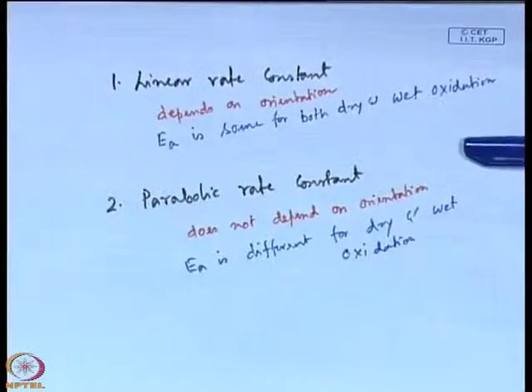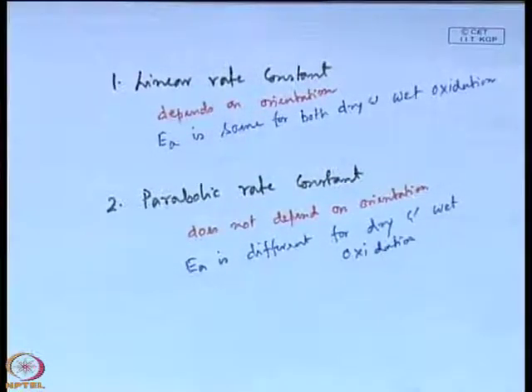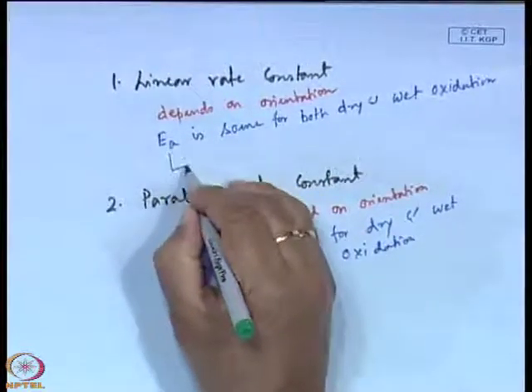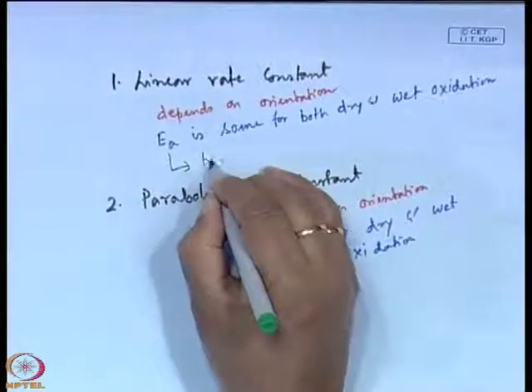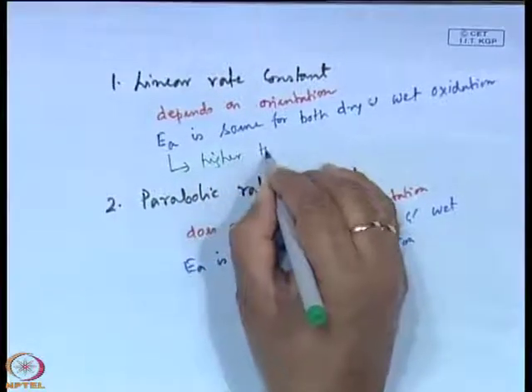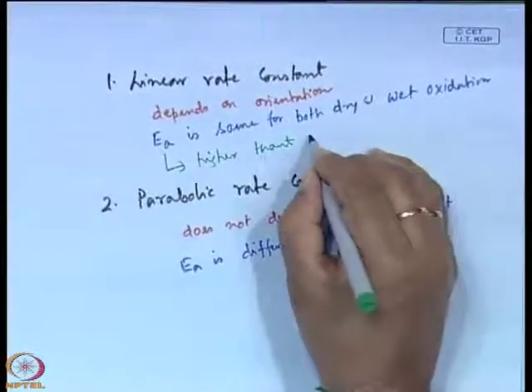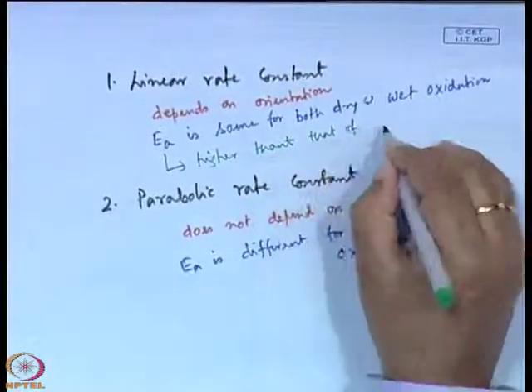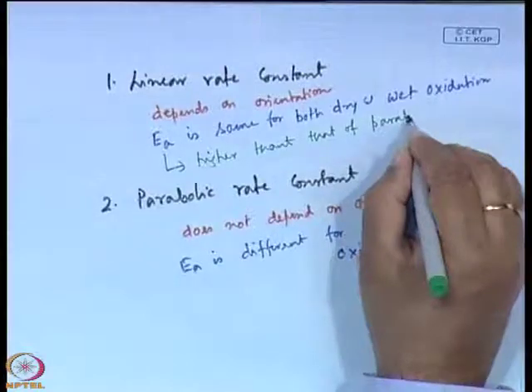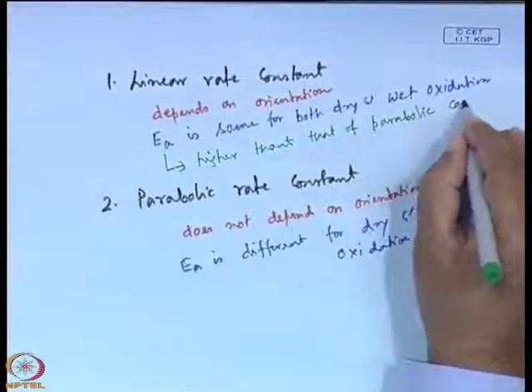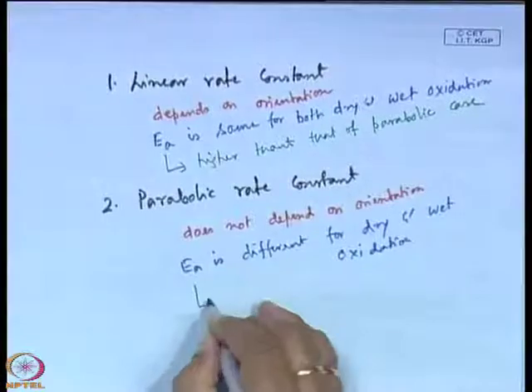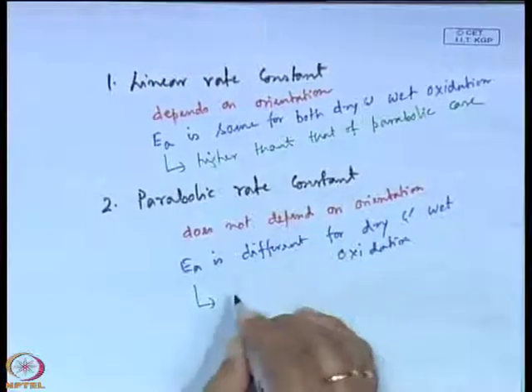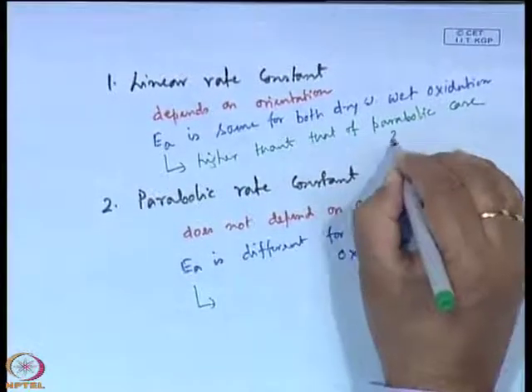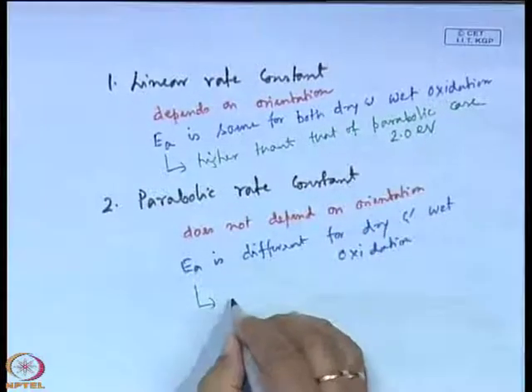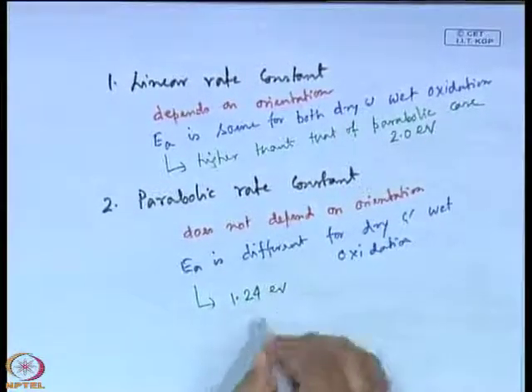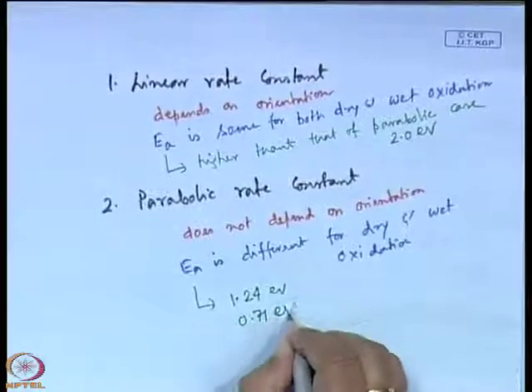And the third difference is the value of E A. This value is higher than that of the parabolic rate constant, and this is lower than the linear rate constant. It is 2 electron volt, here it is 1.24 electron volt and 0.71 electron volt.